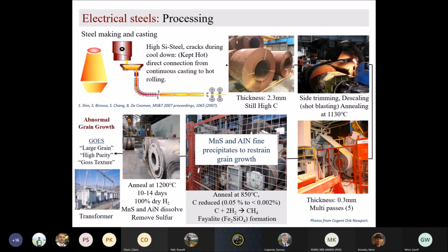Just one point before you go here, if you look at the image after the secondary annealing, you will see the electrical steel is really tired. Imagine you are sitting in a big furnace at 1200 degrees Celsius for 2 weeks. When you come out, you are knackered, right? Steel is the same thing. So when it comes out, the shape is actually not the right shape, and also the sample. That's why they do coating and also thermal flattening to make the steel in shape before they send it to the customer.